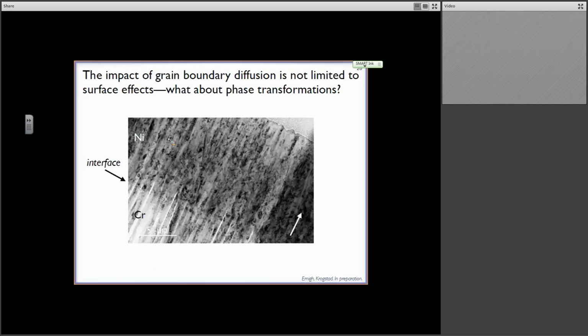Now, I did also mention this idea of grain boundary diffusion: if we preserve the grain boundaries long enough, we get better oxidation resistance. But grain boundary diffusion isn't limited just to surface effects. We saw this when we took the oxygen out of the system and just looked at the microstructure evolution. There are still interesting things happening there. And so we want to think about, well, where else would this accelerated diffusion be interesting or useful? And we can think about this in the context of phase transformations. So first thing we need to do is actually quantify this accelerated diffusion.